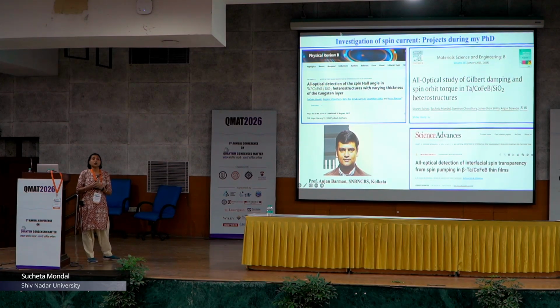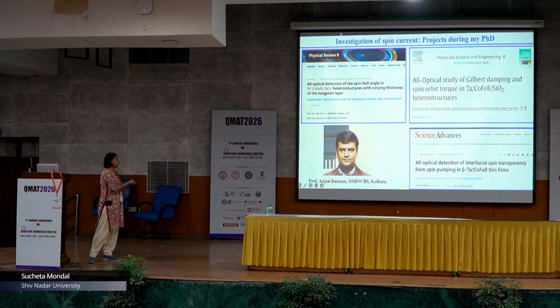We studied all optical detection of spin current in various manner. For example, in heavy metal ferromagnet interface, we sent charge current and then we excite the spin dynamics to the adjacent ferromagnetic layer, and then we could probe the spin dynamics, and from there we can passively detect the spin current conversion efficiency. We also have studied the effect of heat in those devices, and we have also studied, and this is the first report, all optical detection of interface spin transparency, particularly spin pumping in beta tantalum and CoFeB interface.